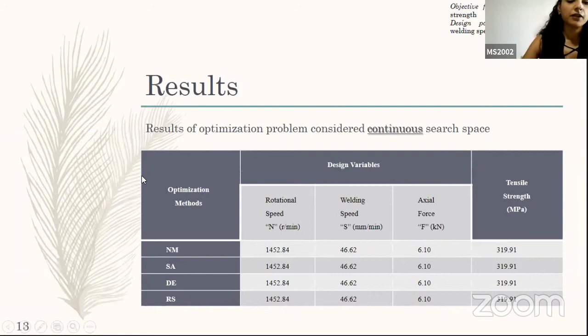The other results: we use different algorithms for the same problem to make our results more reliable. These are Nelder-Mead, simulated annealing, differential evolution, and random search. When we evaluate the results obtained from these methods, we see that the results for the continuous range are all the same, and the global optimum value is 319.91. Due to the precision of the rotational speed, welding speed, and axial force achieved in the continuous range, it is likely to be difficult to apply in terms of engineering.